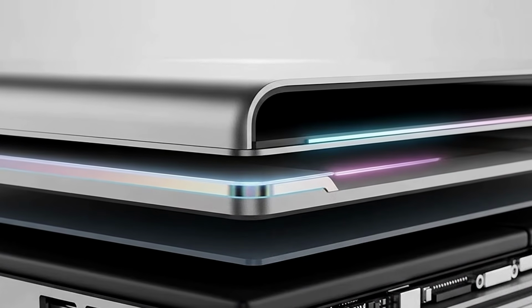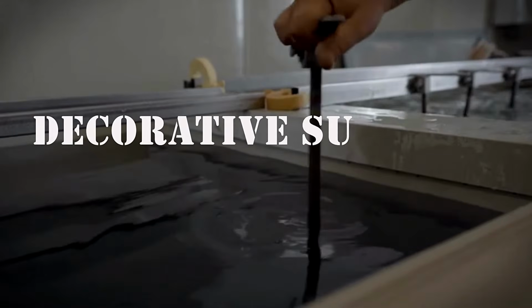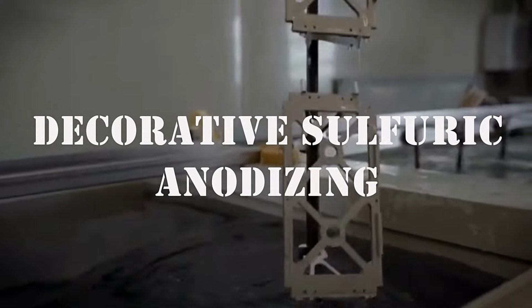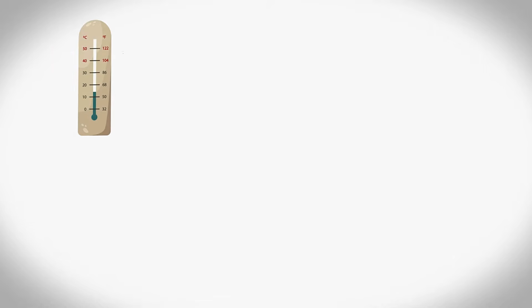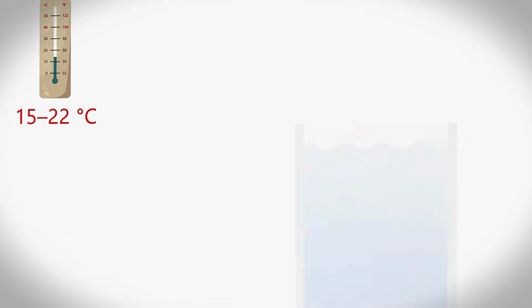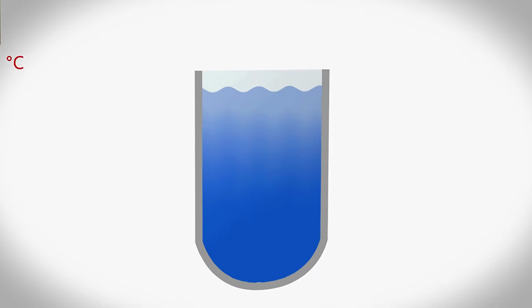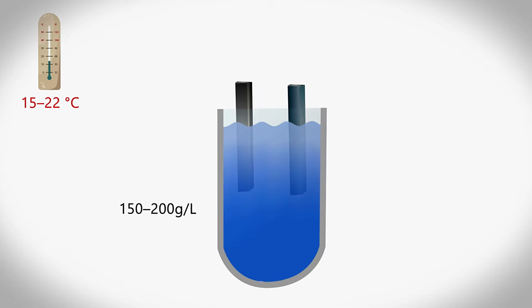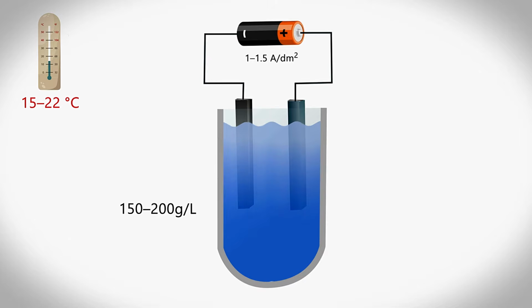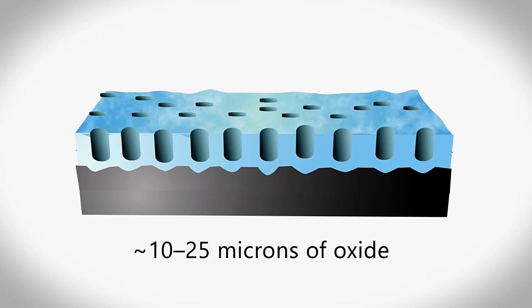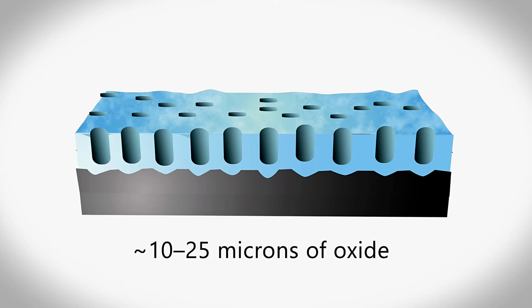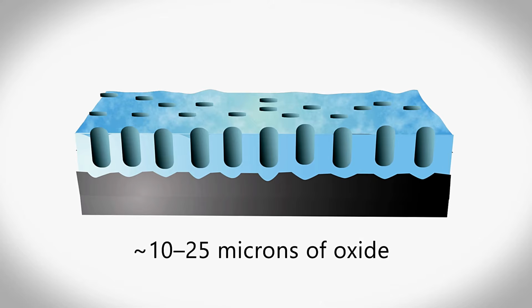For decorative sulfuric anodizing, a typical recipe is roomish temperature, 15 to 22 degrees Celsius, sulfuric acid around 150 to 200 grams per liter, current density about 1 to 1.5 amperes per square decimeter, and 20 to 40 minutes. That gives you 10 to 25 microns of oxide, with pores big enough to dye, but still protective.